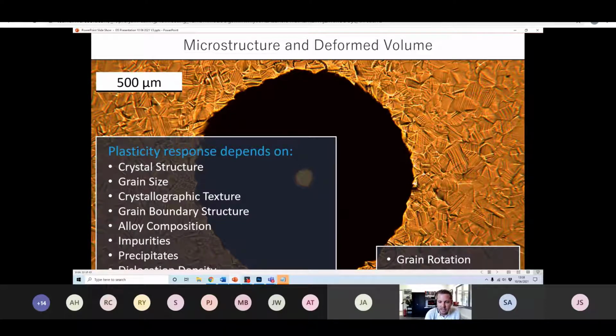Now, the reason that we indent on this scale is because the purpose of our technology is to extract bulk or engineering properties, and that means that you must be indenting a representative volume of material. You absolutely must be capturing all of the microstructural features that give rise to the macroscopic stress strain behavior that you would measure in a common tensile test. If you're indenting into a single grain, as you might be doing in a nano indentation test, you simply cannot get bulk mechanical properties.